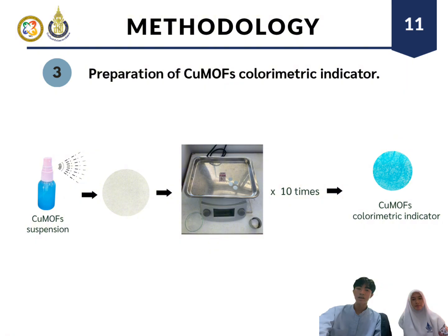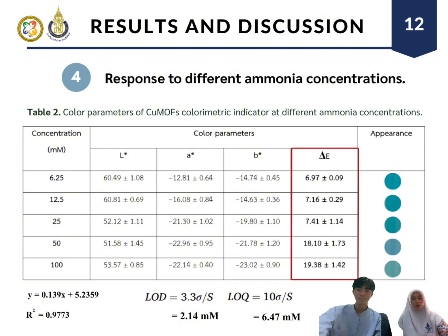Next, the preparation of the copper MOF colorimetric indicator. Copper MOF suspension was sprayed onto a cellulose matrix. This process was repeated 10 times for coating to obtain the copper MOF colorimetric indicator. We tested the response of the copper MOF indicator to different ammonia concentrations. As ammonia concentration increased, the delta E value also increased and the appearance of the indicator gradually changed from turquoise blue to light blue. This is because more ammonia molecules interact with the copper site, changing the local coordination environment of copper.